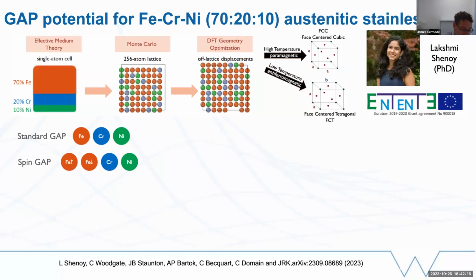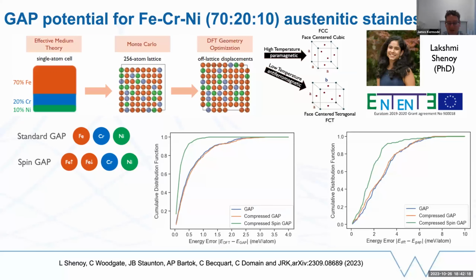But it really leads to a very big improvement, first of all, in the accuracy with which we describe the energies of the target configurations. So we're using the compressions that I described earlier on as well. And we can see that doesn't make too much difference in terms of accuracy. So we have the original GAP model in blue. This is a cumulative distribution function. So it's showing you what the error is, what proportion of configurations have a given error. And we'd like it to be up here in the top corner.